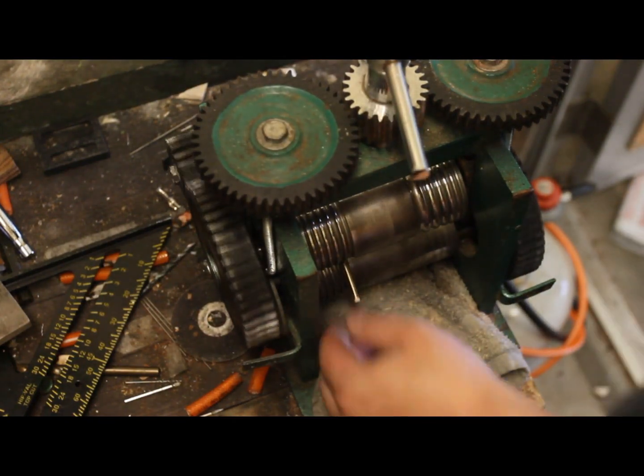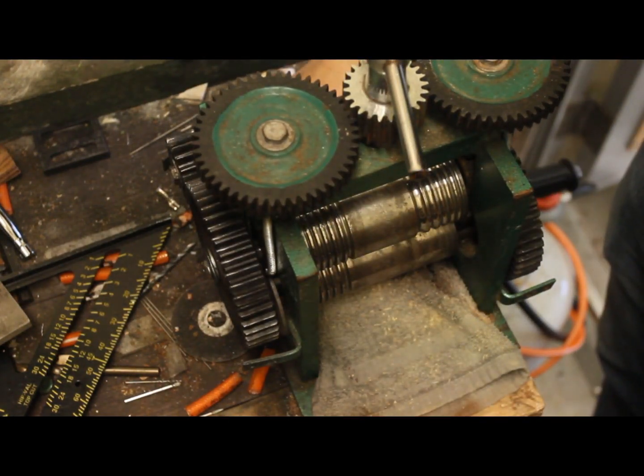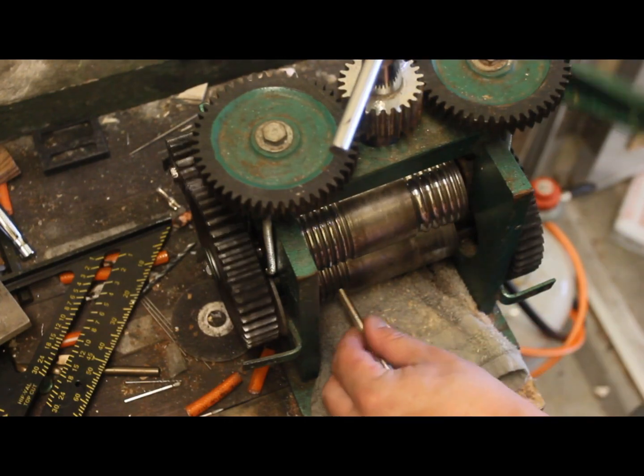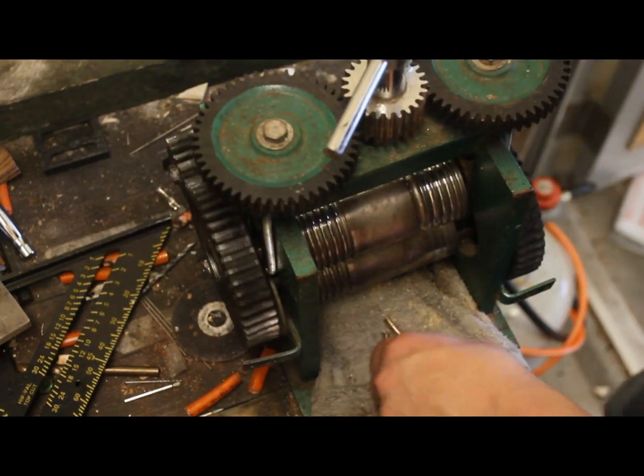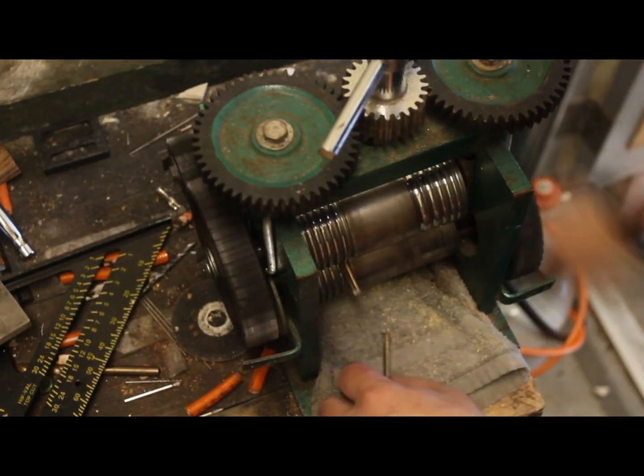Another thing, if you don't get it hot enough when you cast it, and you get an air bubble trapped in there, you're going to find out while you're rolling milling down to square, because you'll end up with a crack.